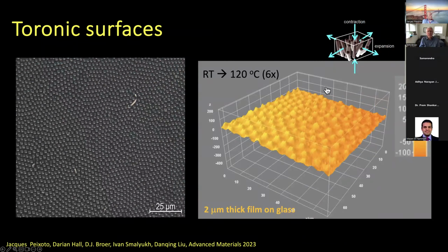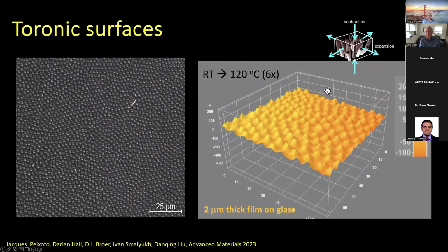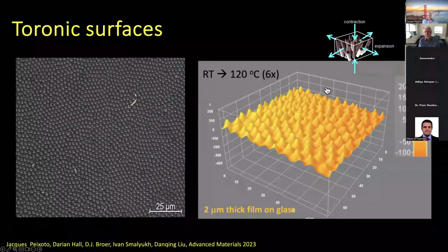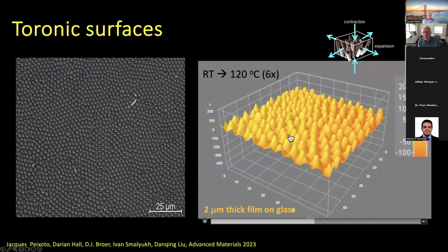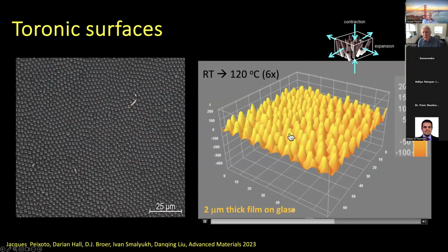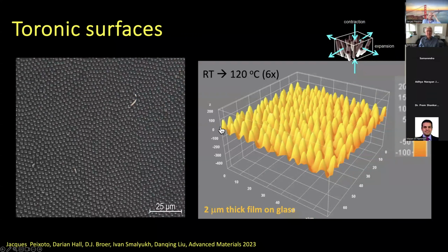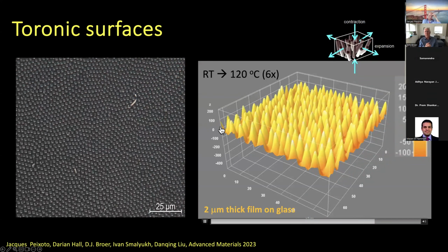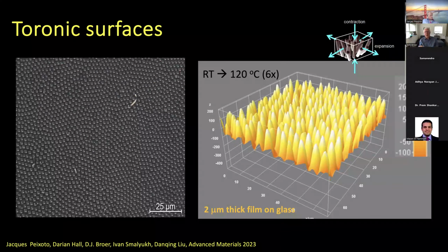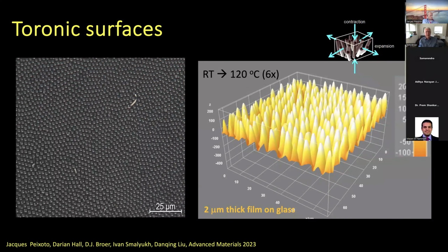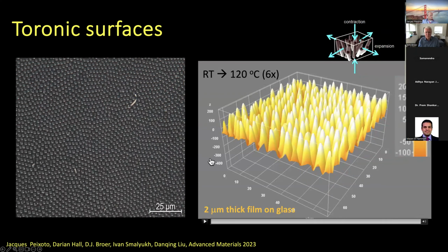In this case, the film covered with torons is heated. And if you look very carefully, you see a little bit of a volcano type of structure. That is where the shrinkage takes place in the toron, and the surrounding is the planar where it starts to expand, and then at the edges it starts to shrink again.